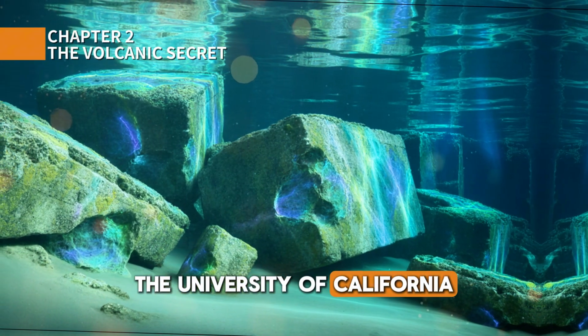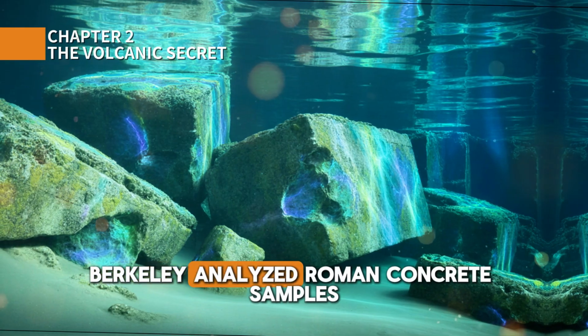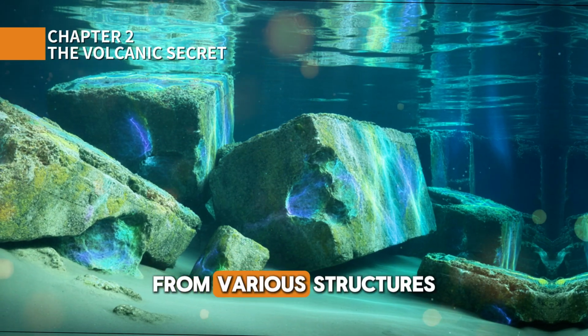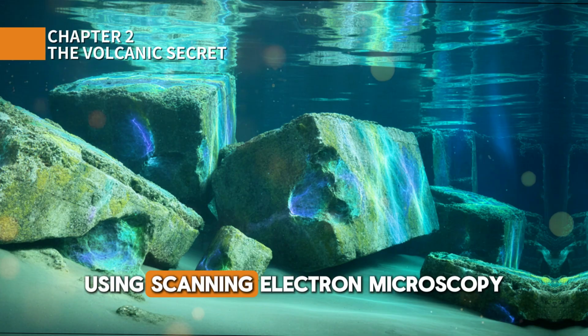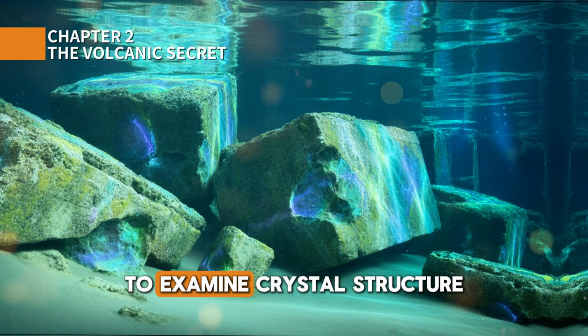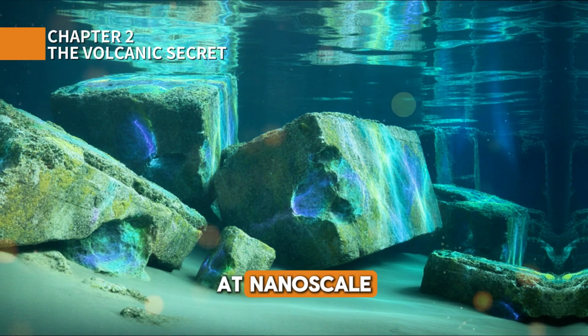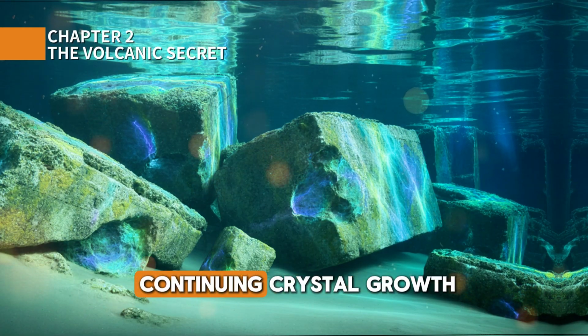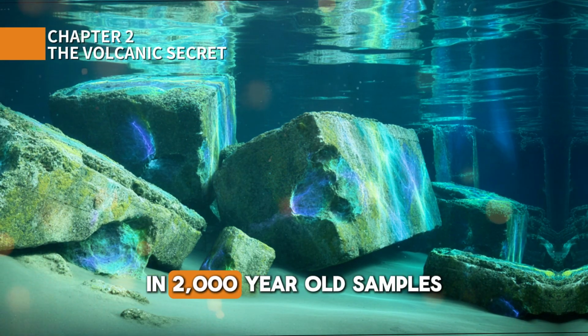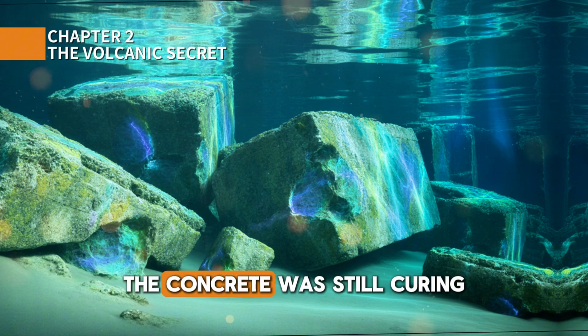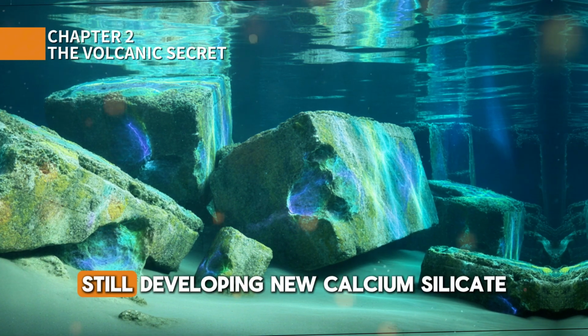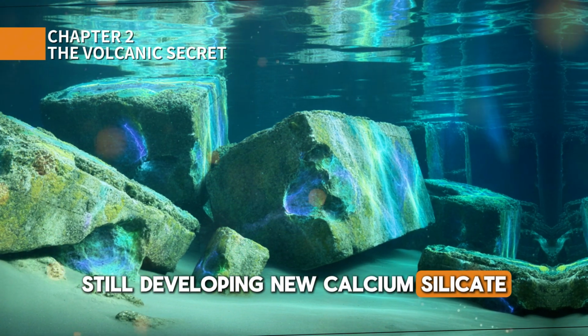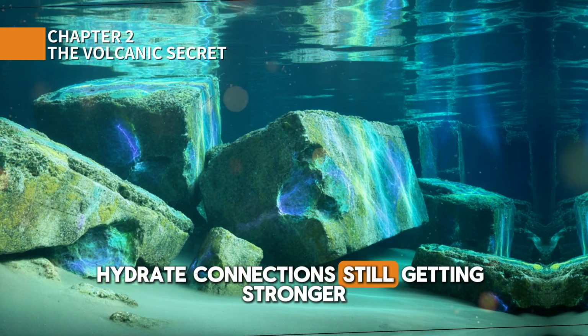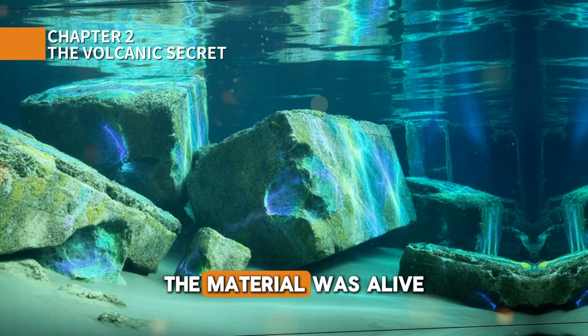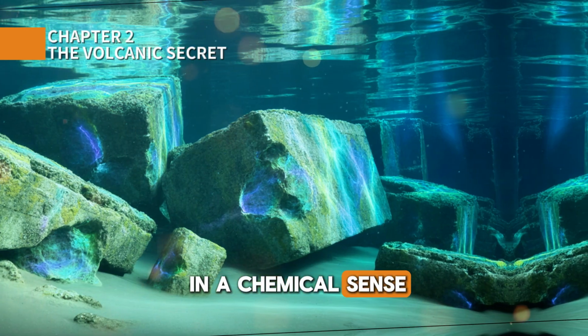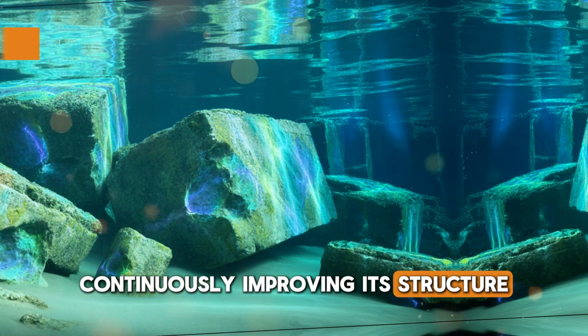The University of California, Berkeley, analyzed Roman concrete samples from various structures using scanning electron microscopy to examine crystal structure at nanoscale. They found evidence of continuing crystal growth in 2,000-year-old samples. The concrete was still curing, still developing new calcium silicate hydrate connections, still getting stronger. The material was alive in a chemical sense, continuously improving its structure.